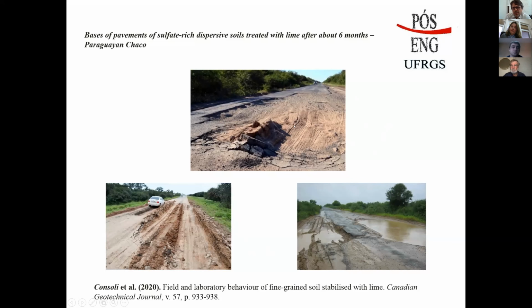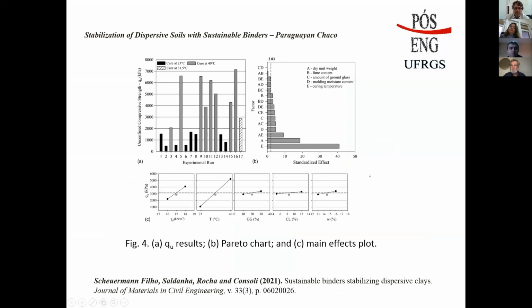This is another problem where you also use some of these materials. This is a soil in Paraguay, in Chaco, which is the western part of Paraguay, where there is a dispersive, sulfate-rich soil, which they usually like to treat with lime, and after less than 6 months, that's what you have there. So the base of the pavement is destroyed completely. This was published in the Canadian Geotechnical Journal also this year. And we have also shown that if you do the same thing that they have done, but add just a small amount of ground glass together with the lime, you have something that is durable and has a large strength.